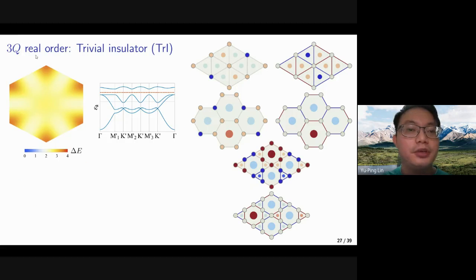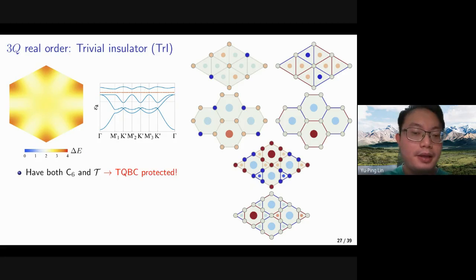The first order we consider is the real order. We can see that if we introduce the 3Q real order, it gaps out the whole Fermi surface, as you can see from the band structure. And there could be some site or bond orders, as you can see from the triangular and honeycomb lattices, and from the kagome flat band and the kagome conical band. Because we have both C6 and time reversal symmetries, the quadratic band crossings are protected.